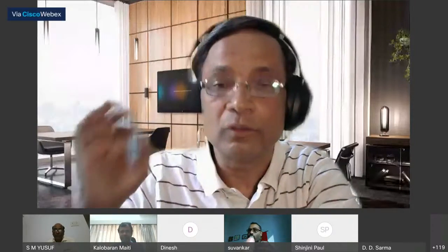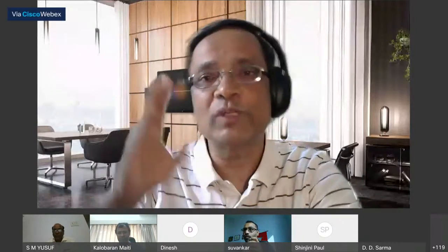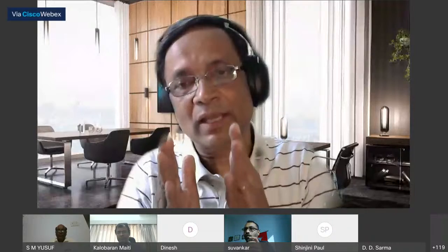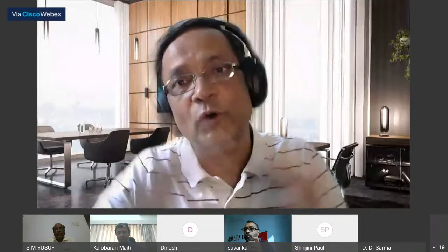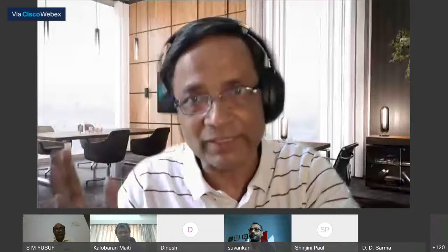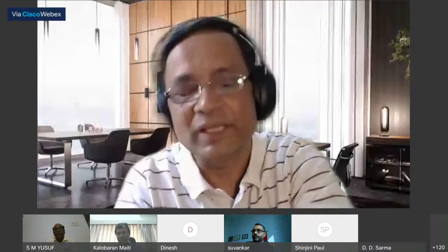Anindya Bhattacharya has a comment, which I'll look at, on very low concentration. If you take this sample and anneal it in oxygen to get rid of oxygen vacancies, as is done in STO, you can get to a very low concentration metallic regime. We do not see anything there. I have those data and I didn't draw your attention to them. It falls below the detection level of photoemission.